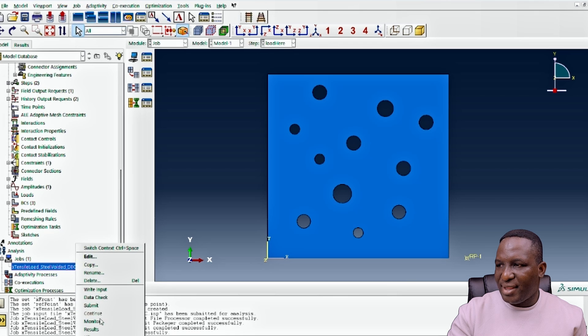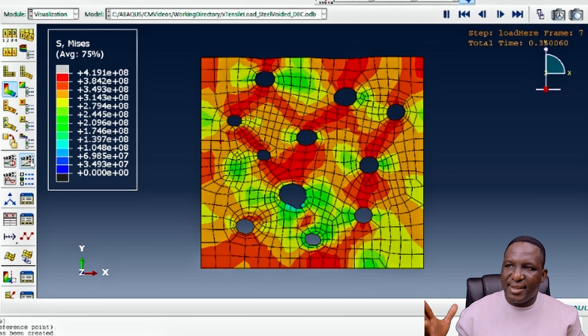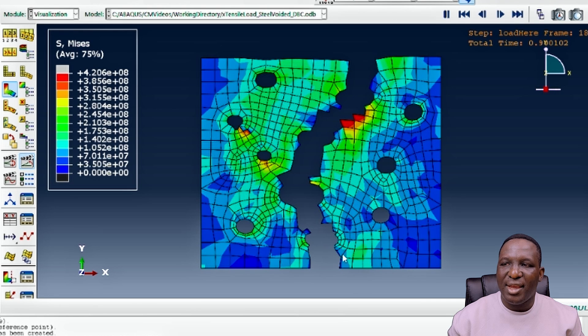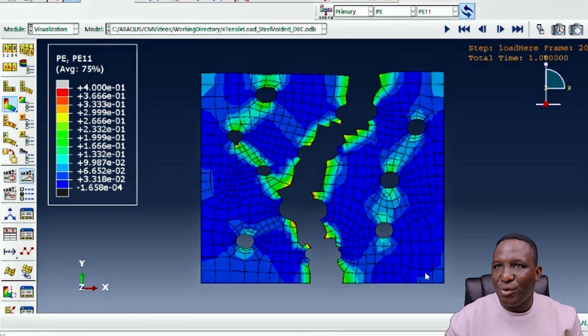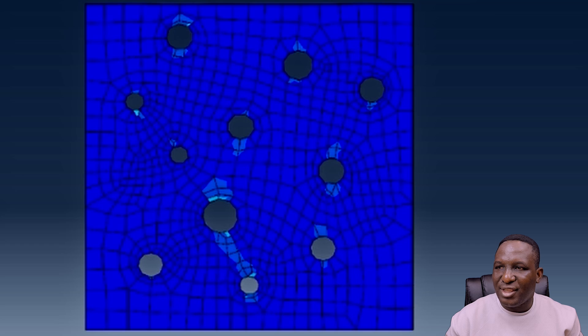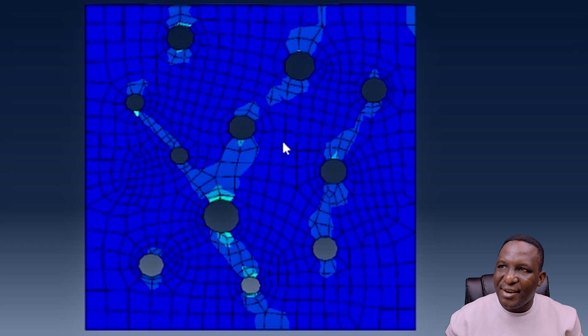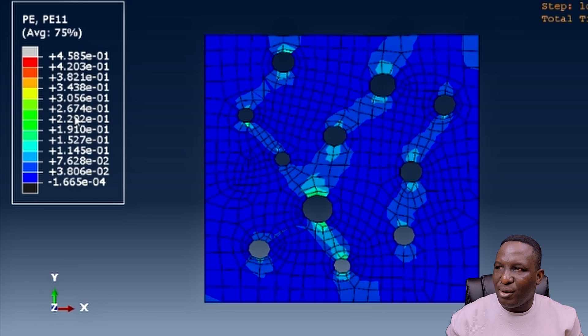The job has finished running and we can view the results. The system starts moving and once cracks form they propagate across the system, leading to a complete fracture. Looking at the plastic strain in the loading direction (direction 1) and stepping through incrementally, we see a build-up of stress at 45 degrees through the material, with regions of weakness initiated by the presence of the voids acting as stress concentrators.